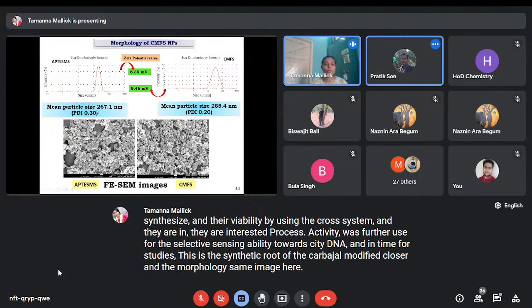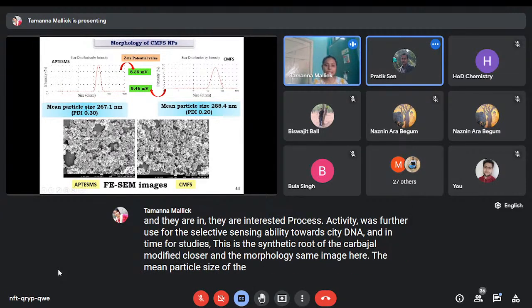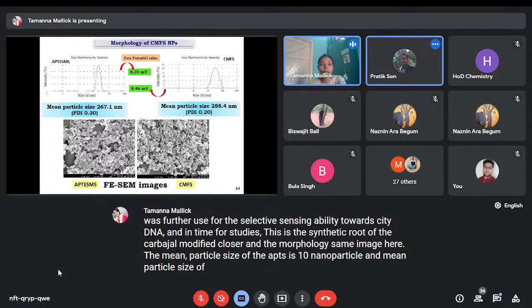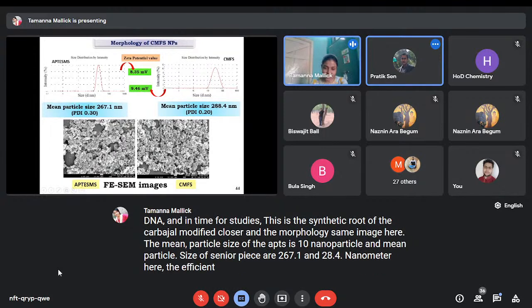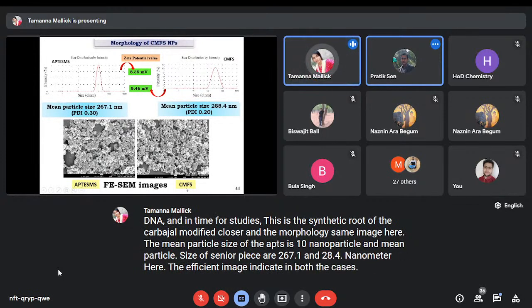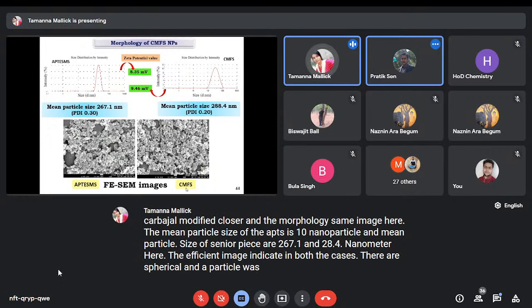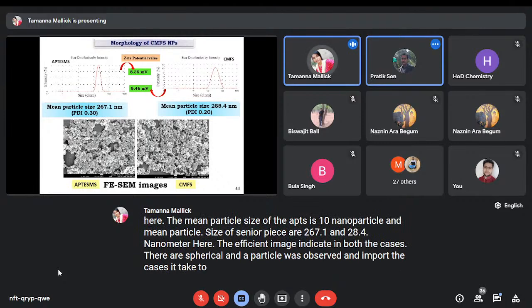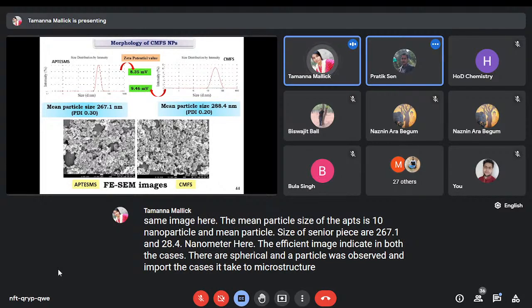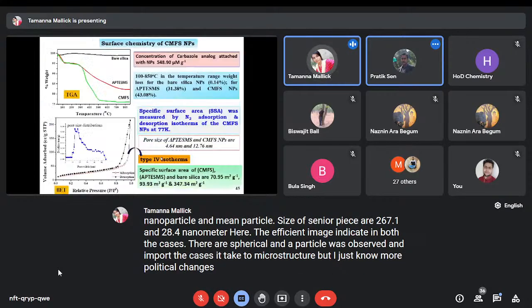The mean particle sizes of the APTESMS nanoparticle and of CMFS are 267.1 and 268.4 nanometer. Here, the FESEM image indicates that in both the cases spherical nanoparticles were observed, and in both the cases a minor aggregated microstructure was observed, but after functionalization of the carbazole, there is no morphological change observed in the case of CMFS and PS.